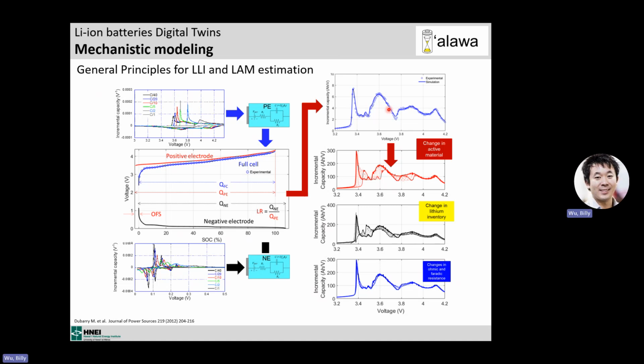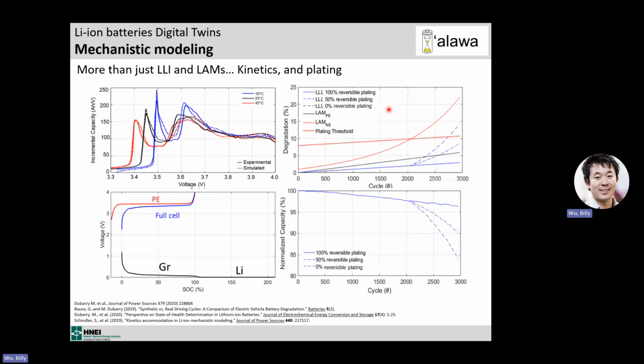But that's a really simple view. It's at low rate, not really kinetic, there's no real complication. So we can look at plating. Plating, if you think about it, that's a blend. Your negative electrode, you have graphite, and when you run out of graphite, you can plate the lithium. So it's a blended electrode, graphite and plating. So you can simply add another phase in the model, add the plating potential of your metal, whether it's lithium or sodium, if you want to use sodium. And so when the model detects that you don't have enough graphite left, whether because you lost too much or the resistance increased too much, it automatically can add plating.